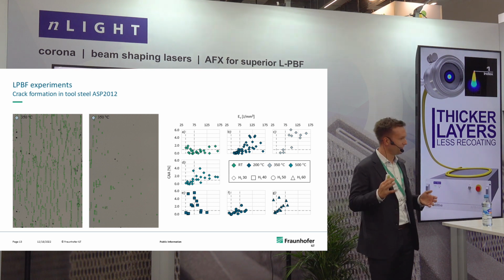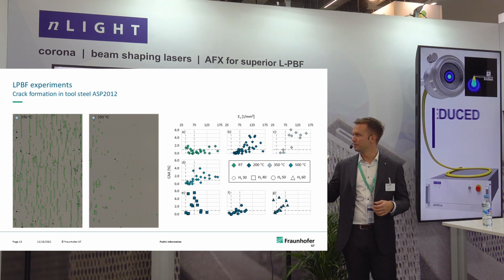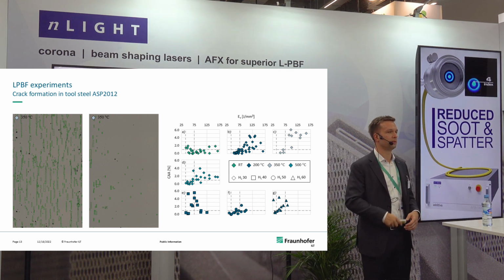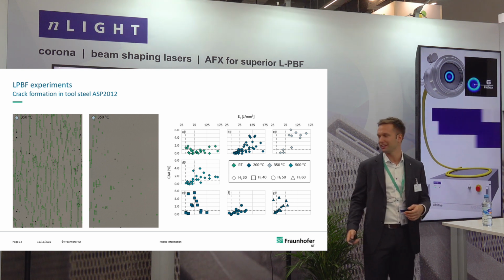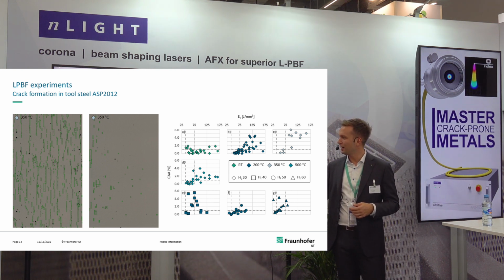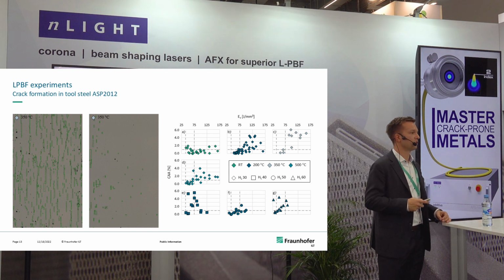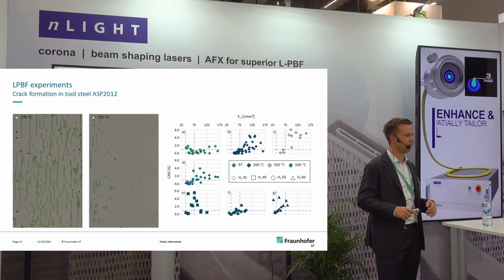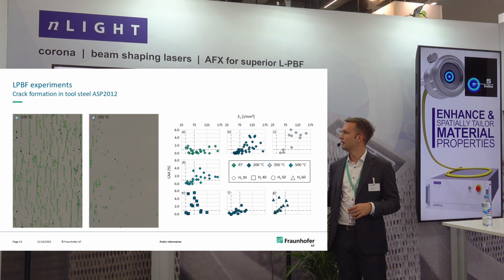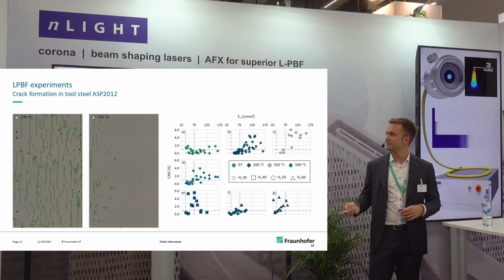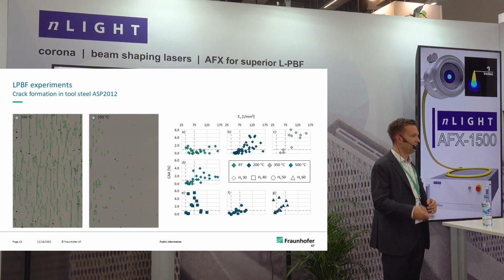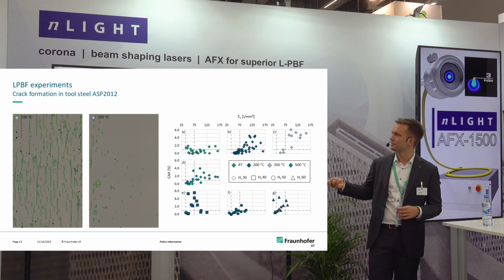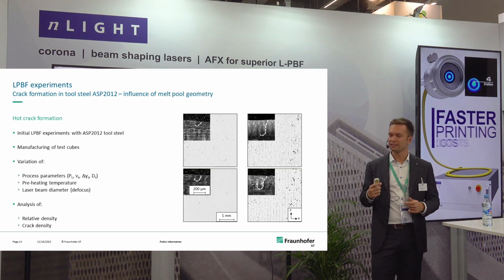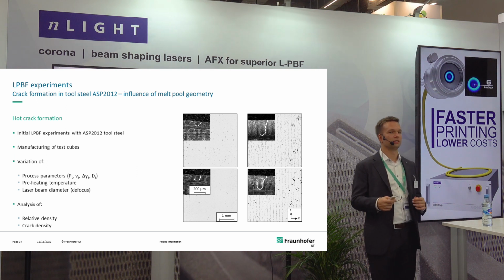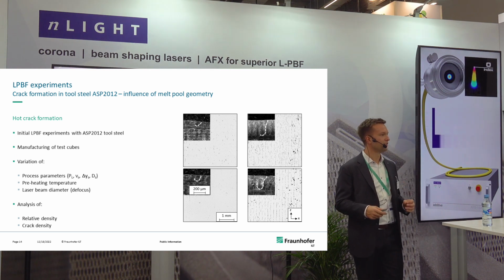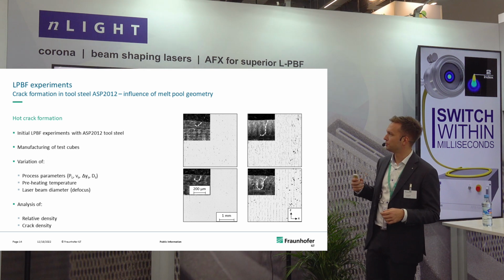You can have more cracks or less, depends. At room temperature it's mostly cold cracks, and then when you go up in temperature it's mostly hot cracking, but you are hardly able to produce crack-free or technically crack-free specimens. And then what we found, as a part of these baseline investigations, was that the amount of cracking really heavily depends on the geometry of our melt pool.